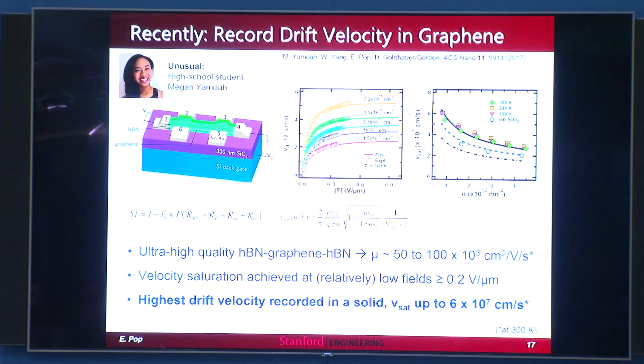More recently, we came back to re-examine this high field transport problem. But this time, we worked with Professor David Goldhaber-Gordon. David is in physics at Stanford, and he really likes to work on very, very clean systems. He said, forget SiO2, that's a bad substrate. Let's use boron nitride. Boron nitride is an ultra-flat 2D layered insulator with large phonon energies, it turns out. And so the mobilities that we can get in graphene on boron nitride are approaching 100,000 at room temperature. So these are incredible mobilities. These are incredibly good samples. Very difficult to make. These are made with Scotch tape, by the way, one at a time.